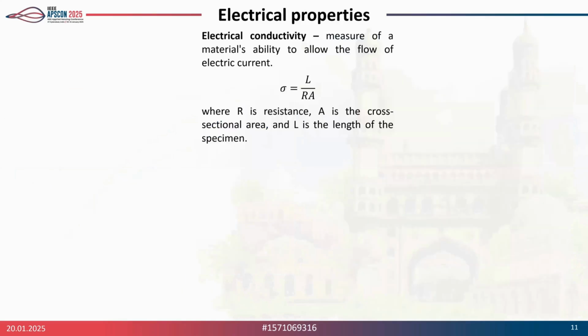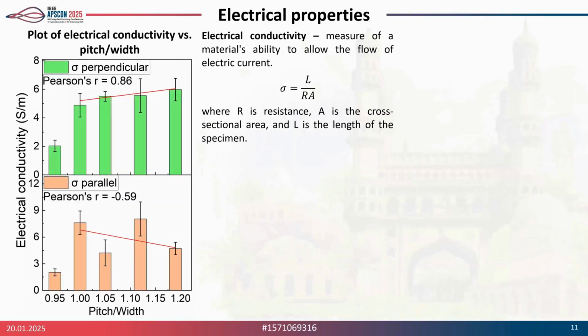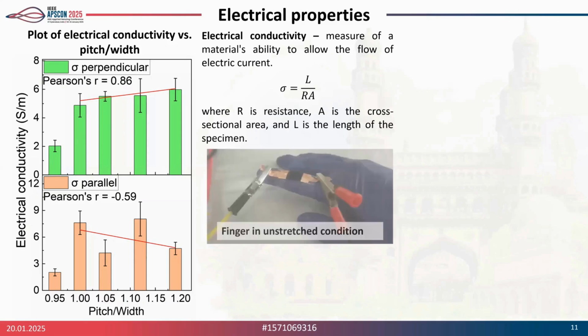Third, and the most important, is the electrical conductivity part. We measured the electrical conductivity of all the sensors and plotted it against the parameter known as pitch by width. Pitch is nothing but the distance between the grooves that we prepared, the peak to peak distance, and the width is basically the width of each microgroove. It also showed a good correlation with the electrical conductivity.